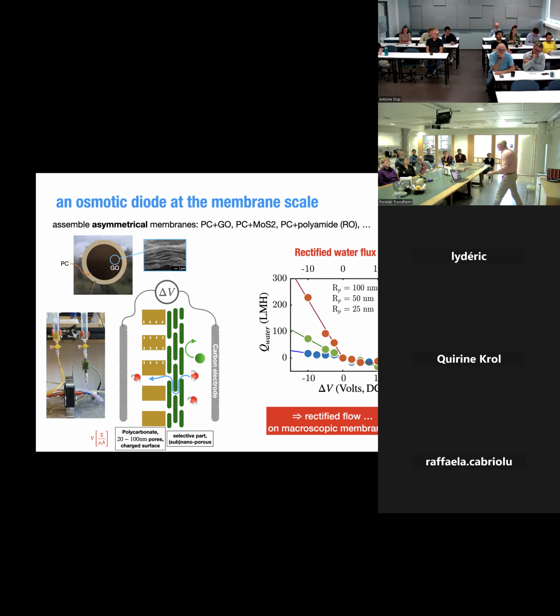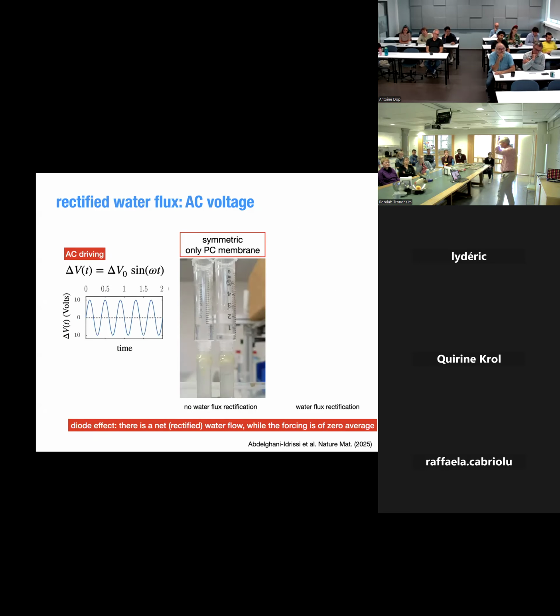Actually, another way to show that is to play with AC voltage. So instead of applying a direct current voltage, you apply AC. First, I show you what happens with only the polycarbonate. There is no rectification there, so it should go one way or the other. And indeed, when you go forward, backward, nothing happens.